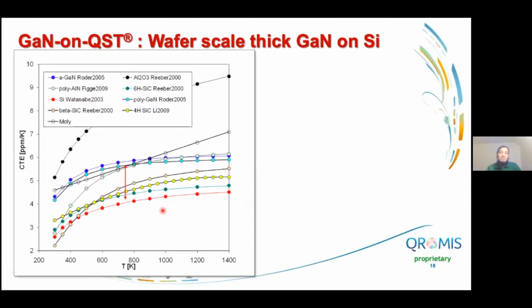So to overcome these problems, we collaborated with a company, Qromis, which has a patented technology they call QST engineered substrate technology. The key to this technology is the substrate itself. In this plot, we have the coefficient of thermal expansion for different substrates that can be used for gallium nitride. The red one represents the CTE for silicon, and this curve is for gallium nitride. As we can see, the CTE mismatch between silicon and GaN is really high, which causes the epi to crack if we just grow thick epi directly on silicon.